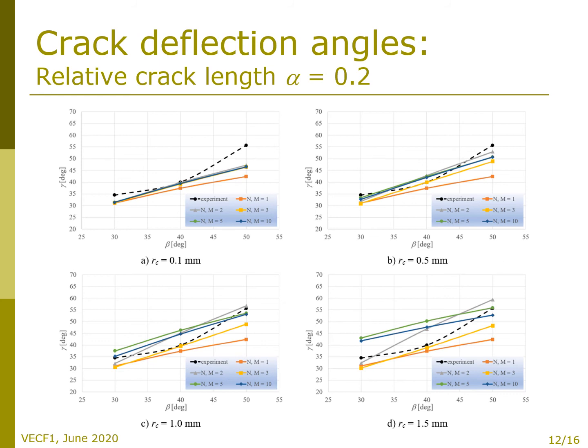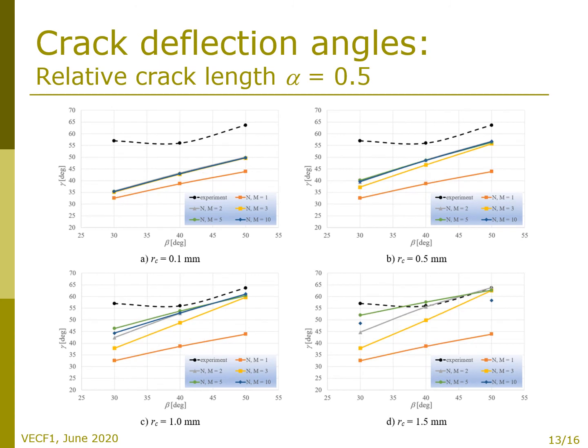Each plot is related to another critical radial distance, 0.1, 0.5, 1, and 1.5. Analogical results have been obtained for longer cracks with their relative length of 0.5.